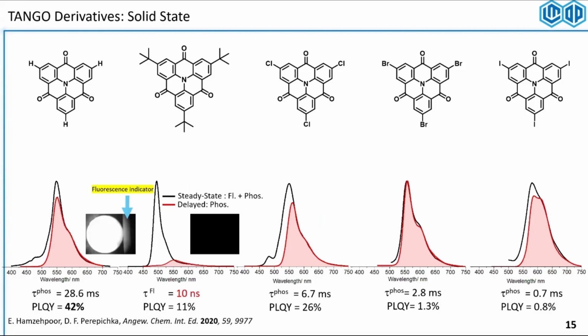In the solid state, I could clearly see that all the halogenated derivatives were highly phosphorescent. The non-substituted Tango was phosphorescent, but the tertiary butyl Tango was not. Here you see the black emission. It's the total emission. You shine light on the sample and you collect whatever light comes off of it. In the red, you see a delayed emission where you shine light, you wait for normally a microsecond or a millisecond, and you start collecting the light that comes as an afterglow. So you eliminate all the fluorescence of the system.